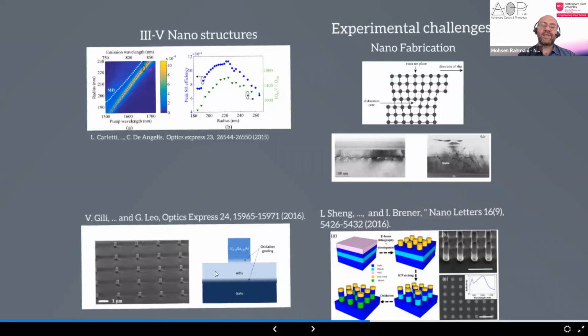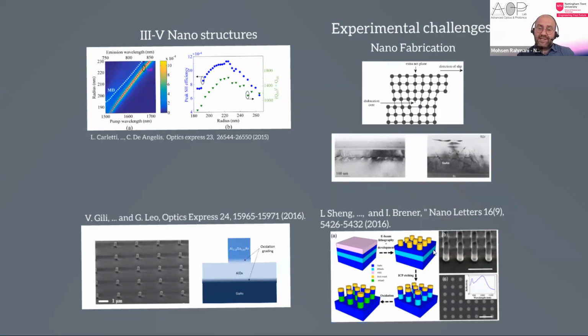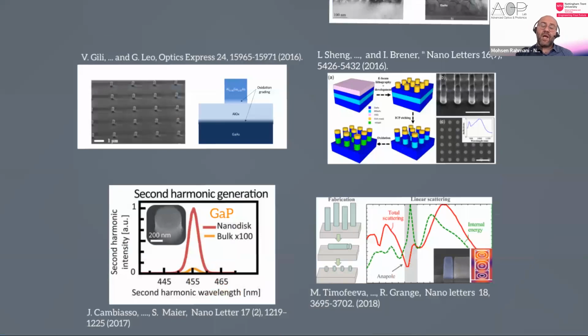As you see over here, for example, Giuseppe Leo's group did aluminum arsenide, then oxidized it to aluminum oxide, or the group of Igal Brener used aluminum gallium arsenide as the sacrificial layer, then they made it aluminum gallium oxide. So as the result, on the top, they had these isolated gallium arsenide or aluminum gallium arsenide nanoparticles, which could generate nice nonlinear signals.